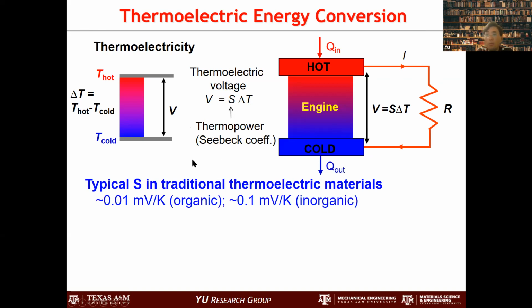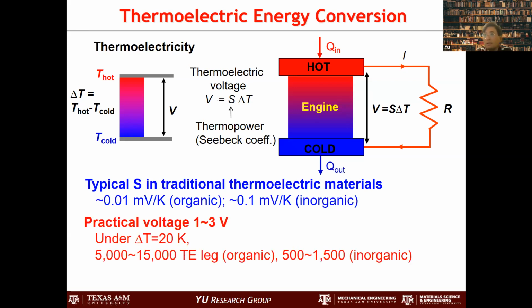This factor is called the Seebeck coefficient or thermopower, and typically this value is actually quite low. For organic material it is about 0.01 millivolt per Kelvin, and for inorganic material about 0.1 millivolt per Kelvin. So unless you have a really high temperature difference, the voltage that you can get is tiny. A typical device requires about 1 to 3 volts. If you think of a dry cell, it's about 1.5 volts, right? Then under, say, a 20 Kelvin difference, you need a huge number of these materials connected in series so that you can boost up the voltage. But this is kind of impractical. It's too many, right?